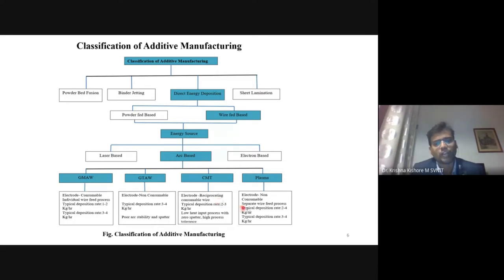So if we see almost all the heat sources, we are able to achieve a minimum of 1 kg per hour deposition. But there are several advantages and disadvantages with different heat sources. Mostly in industry, people prefer either cold metal transfer or plasma arc welding, where the spatter is very, very low. We will see why the spatter is less in the subsequent slides. And we will see what happens if the heat input is very high and how the grain size grows.